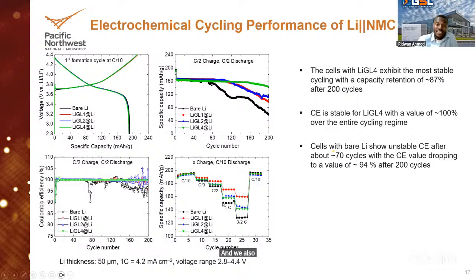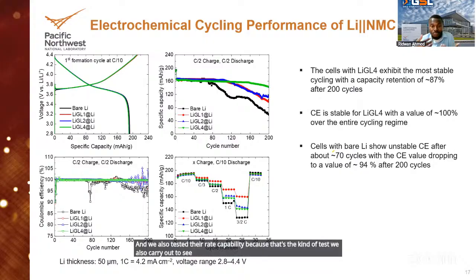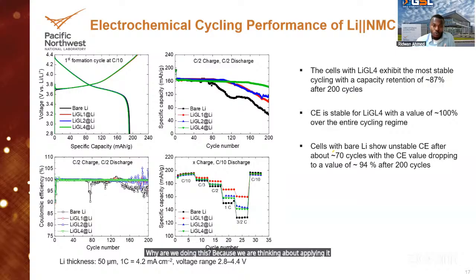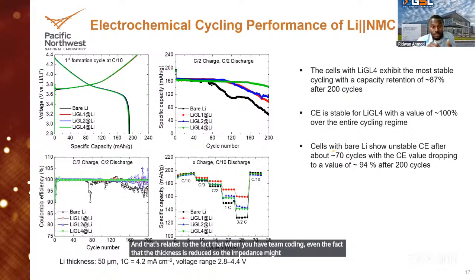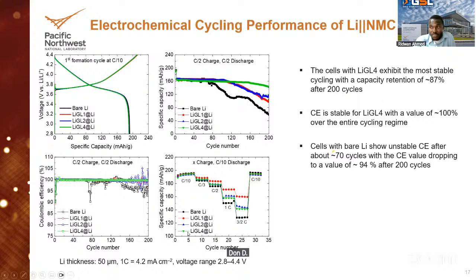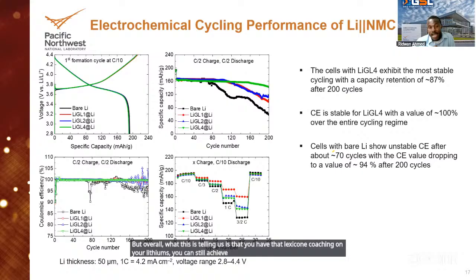We also tested the rate capability, because that's a test we carry out to see how this battery behaves if we charge it very fast. Why are we doing this? Because we are thinking about applying it for EVs. We want to charge the batteries as fast as possible so that it can compete with gasoline vehicles. If you look at this, it looks like the thinner coating on lithium actually performs better here. That's related to the fact that with a thin coating, the impedance might be slightly lower than the thicker coating. That's why we achieve higher capacity here than the thicker sample, which is the green line. But overall, what this is telling us is that if you have that lithium coating on your lithium, you can still achieve higher capacity even at fast charging rates.